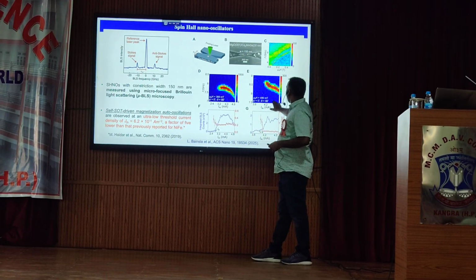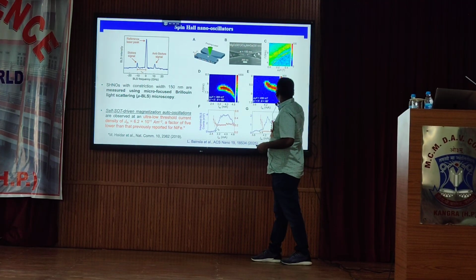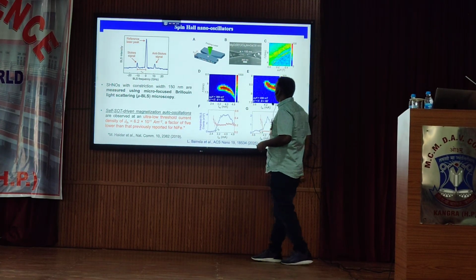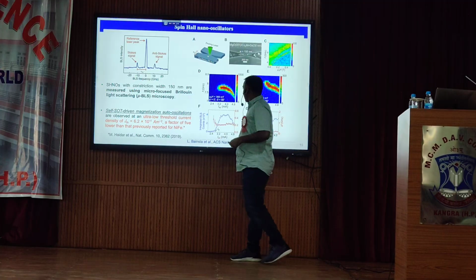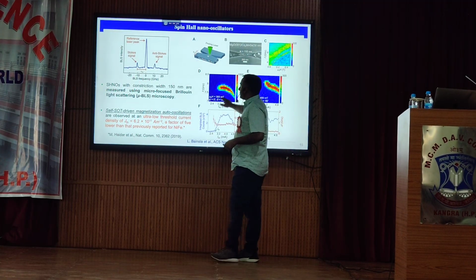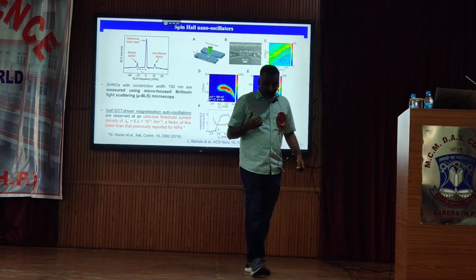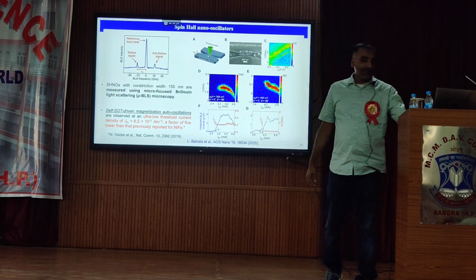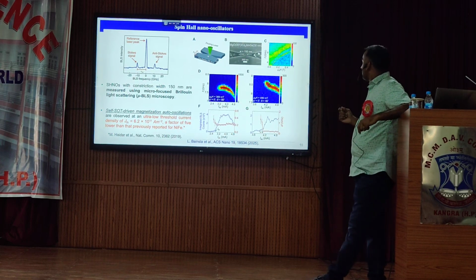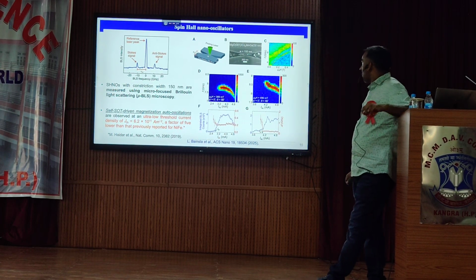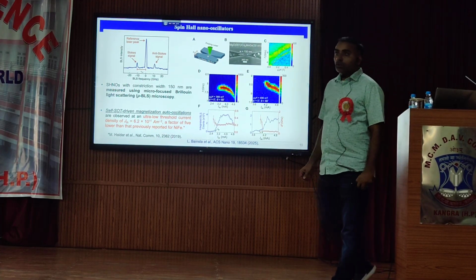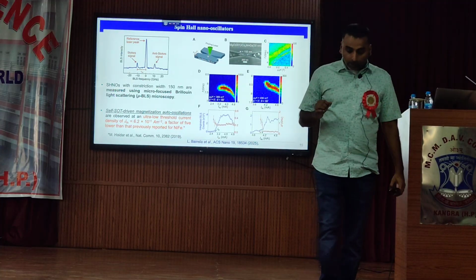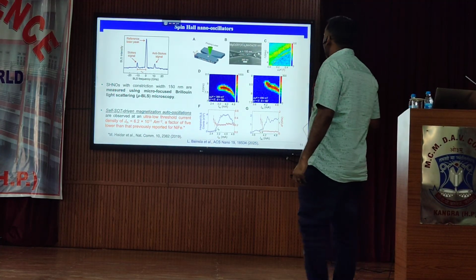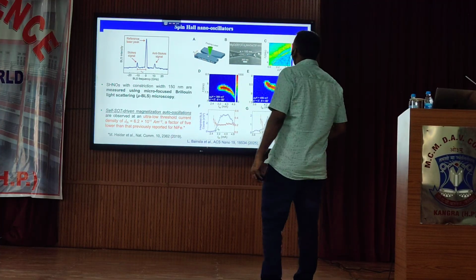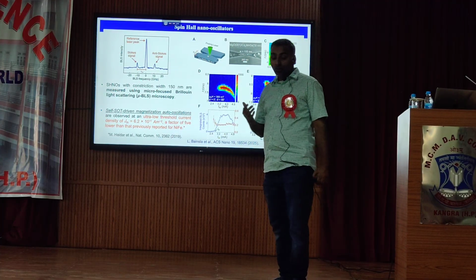And as you can see here, we were able to see the magnetization auto-oscillations. This is the Brillouin light spectroscopy count. So we can see the magnetization auto-oscillations at very low current densities. For this sample, we were able to see them at very low current densities. If we compare with the existing magnetic materials, the value we got here is almost a factor of 5 lower than the previous values. So with this material, we were able to reduce the power consumption of the spin Hall oscillator by 5 times. I think this is very good news, considering how we can use quantum materials for the benefit of society.